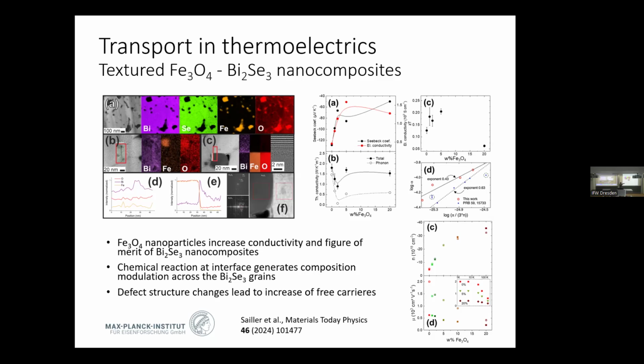It's just a compositional modulation in length scales of 50 nanometers, something like that. In that situation, we had a tremendously increased electrical conductivity. You see it in the red dots, up to a certain amount of the secondary phase of the iron oxide. Because after that, when you have too much insulating phase, then things start to go bad again. But up to some point, we profit from this chemical effect and increase the conductivity largely.